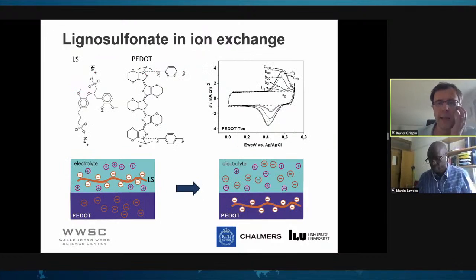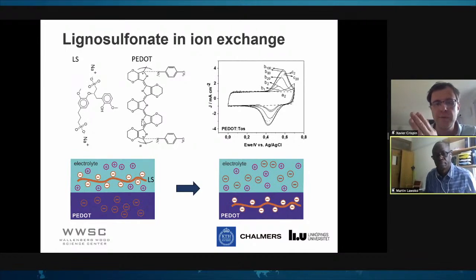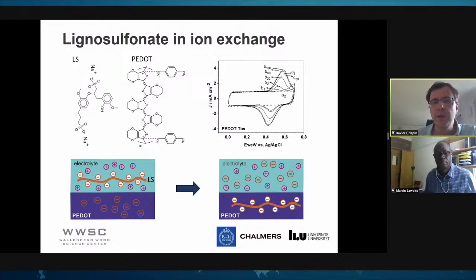In that case, what we did is we synthesized a nanoparticle as well as a film of PEDOT tosylate. PEDOT is a conducting polymer that is positively charged, and the tosylate is a sulfonated small molecule that is negatively charged, and it is compensating that. So when you have this film and we dip it in a solution of lignosulfonate, what we observe is that the lignosulfonate is actually going not only on the surface of the material, but really inside.